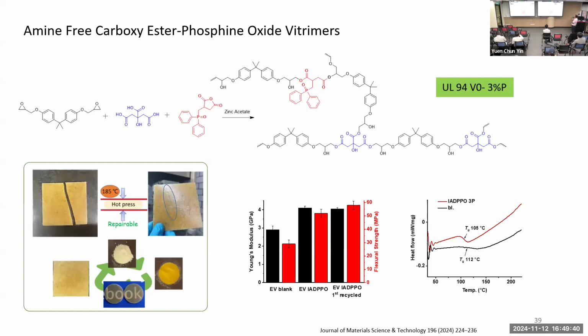What I showed you was a covalent adaptable network where phosphorus was part of the network, built into the network. Here, you have another chemistry which is called carboxyester chemistry, where the phosphorus is not directly part of the network. The phosphorus is not the one which links the different polymer networks. Okay, so this is a chemistry which is also amine-free. It uses a bio-based acid to network the structure, and it's called carboxyester chemistry, where phosphorus is dangling to the side, I would say.